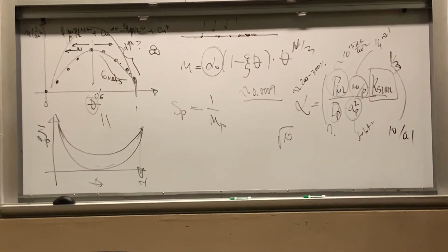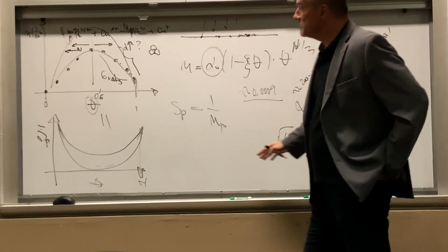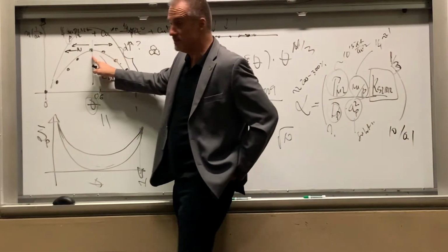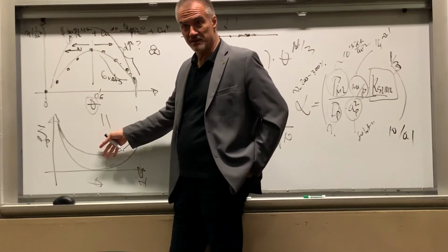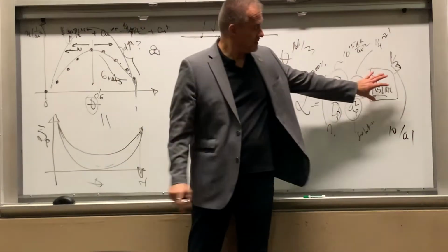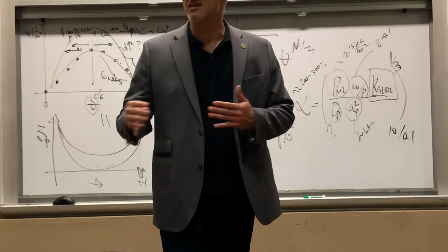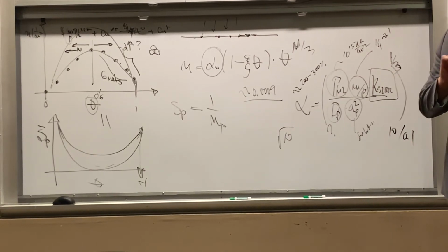Is that a fact? Yes. So what that means, 200 to 300%, is that I can change the cluster size by taking care of this, because a 10 times faster reaction is easily achieved, as you will see. Or a 10 times slower reaction. Depends what kind of catalyst you want.